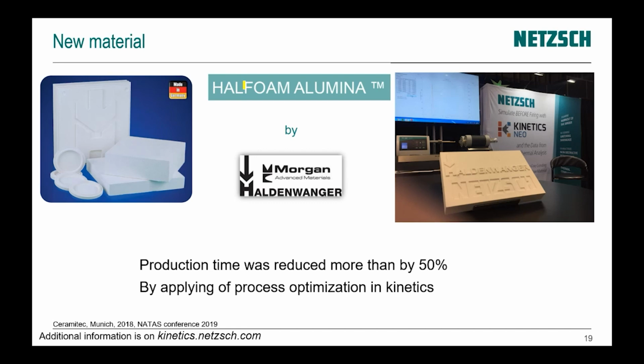And after our optimization, we made measurements in the laboratory, created a kinetic model, and then provided the optimized temperature profile for production of this new material. During our optimization, we reduced the production time by more than 50%. And these results were presented at the Ceramitec and NATAS conferences. So that was the first one.